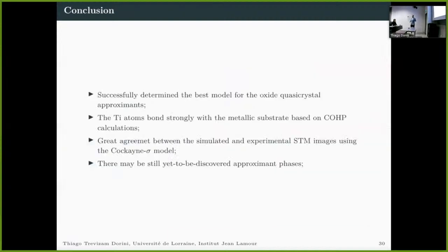So this leads us to the conclusion for this first part, which is: we successfully determined the best model to represent these oxide quasi-crystalline approximants. We see that the titanium atoms specifically bond strongly with the metallic substrate based on COHP calculations. There was great agreement between the simulated and experimental STM images used in this model. And there may still be other approximant phases yet to be discovered.